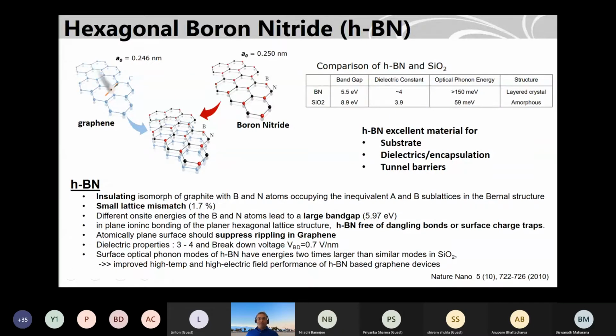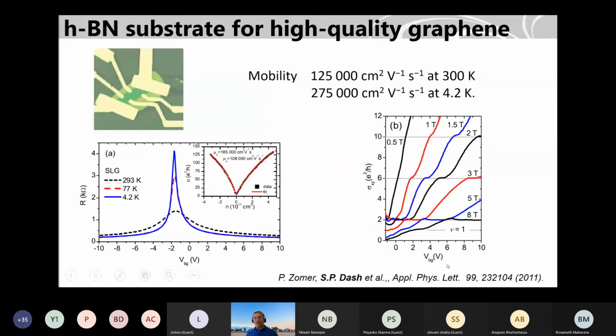So the one thing one can do is use boron nitride. Boron nitride, maybe all of you know already, is an insulator, and it's quite lattice matched with graphene, and quite a perfect insulator. But it doesn't have a dangling bond. So that is quite interesting. And I also worked with such systems, and we get very high mobility graphene on boron nitride.